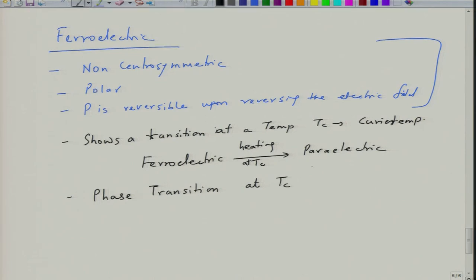So, generally this transition will be from a non-centrosymmetric to a centrosymmetric phase. So you can see the terms are similar. Just like in magnetism, we have paramagnetic, we have paraelectric here. Just like we have ferromagnetic, we have ferroelectric here. So there is a transition from a non-centrosymmetric phase to a centrosymmetric phase at a temperature TC. And this TC is called the Curie temperature.